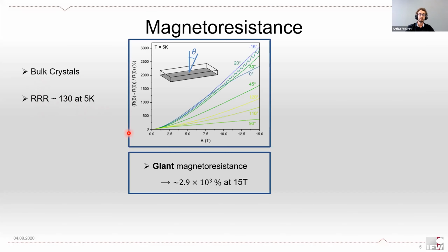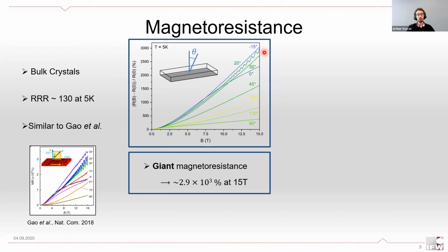And then we looked at the magnetoresistance in our sample. So here you can see the magnetoresistance versus magnetic field for a range of tilting angles of the field, 0 corresponding to a perpendicular field and 90 degrees to a planar field. For perpendicular fields, we found a bit more than 2000% magnetoresistance at 15 Tesla, which puts this sample into the range of giant magnetoresistances. But you can see that the maximum of magnetoresistance is not reached for perpendicular fields, as is usual, but for a field tilted away by about 20 degrees. So this has already been observed previously with quite close values in terms of the angles.